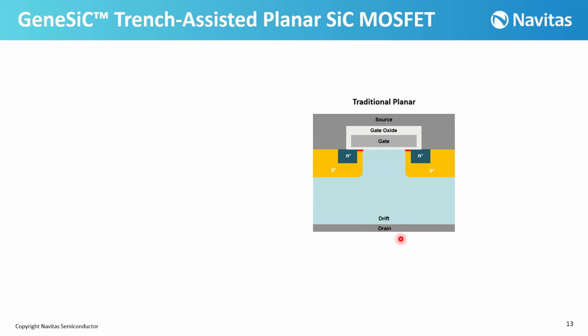But there is one challenge between silicon carbide and silicon, or let's compare the silicon and silicon carbide. Actually, the electron mobility in silicon carbide is lower than silicon, which obviously will increase the RNSP, or specific on-resistance. In order to reduce this parameter, RNSP, there are different ways. One way is reducing the cell pitch, so we can shrink the device. And another way is reducing the gate oxide here in order to improve the channel mobility and improve the RNSP.